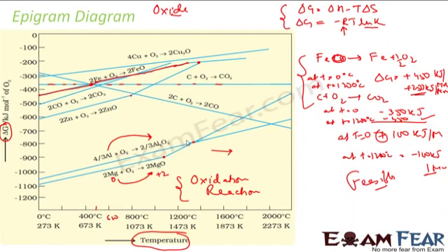So actually in this range of temperature, magnesium can reduce these oxides, aluminum oxides. See, the rule is pretty simple. At a given temperature, for example here, right? So this magnesium metal will be able to reduce any of the oxides. It can reduce aluminum oxide, it can reduce zinc oxide, it can reduce carbon dioxide, even carbon dioxide also through carbon. So this magnesium is a good reducing agent.